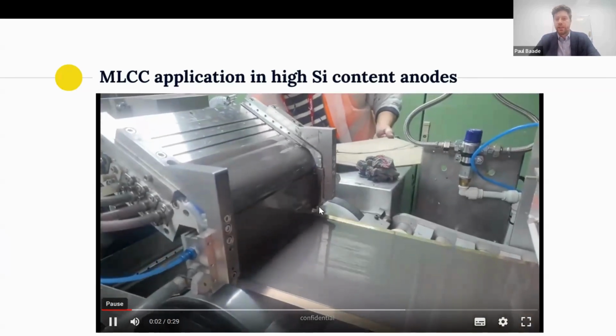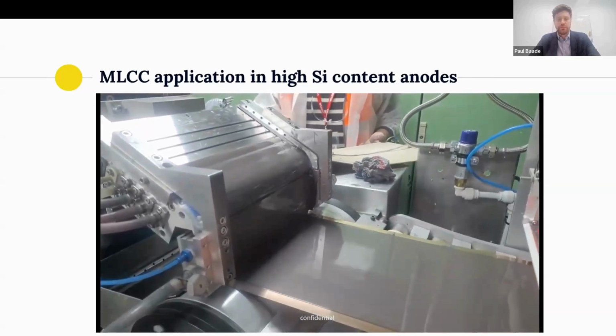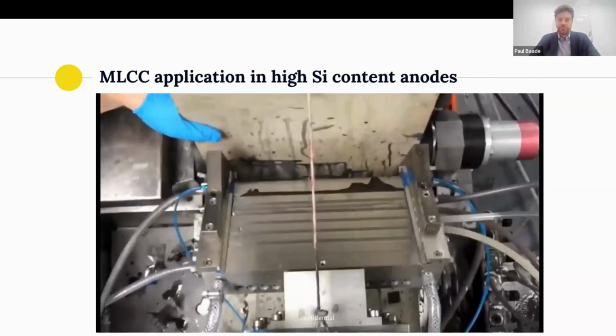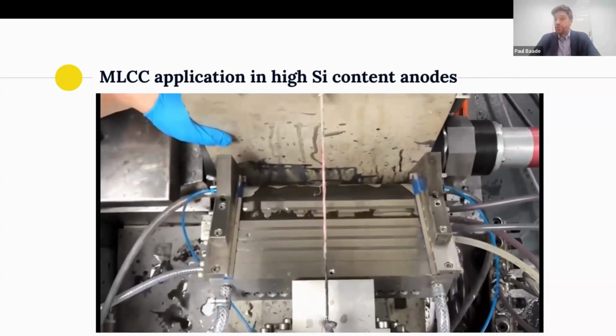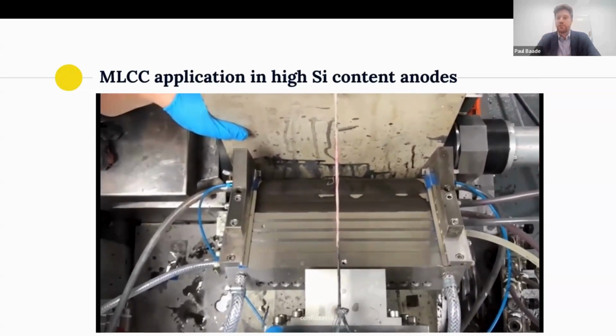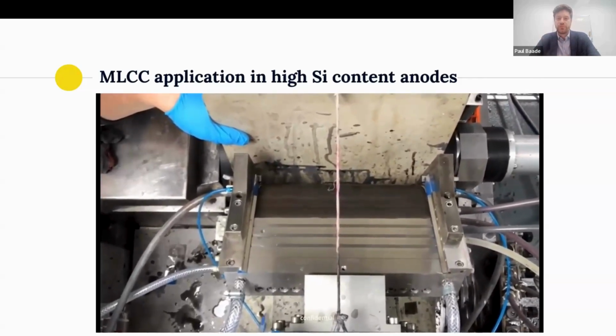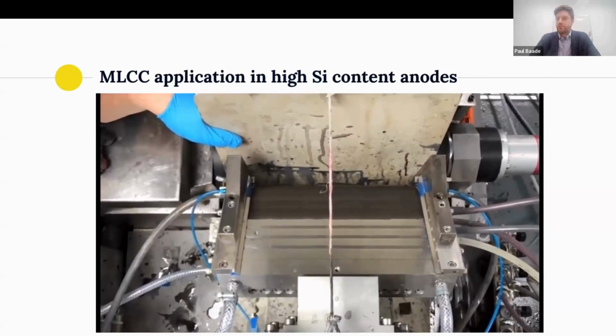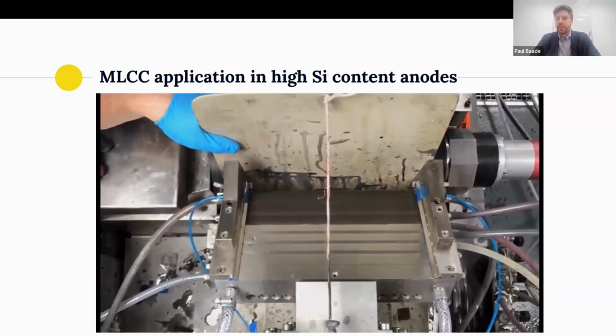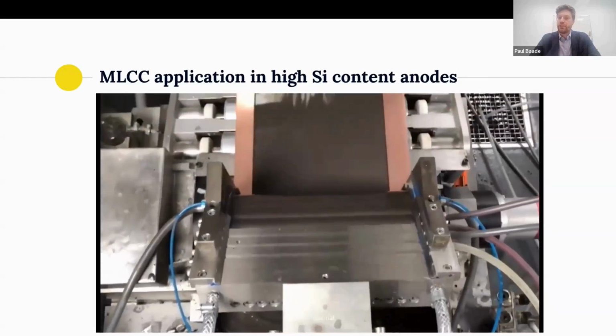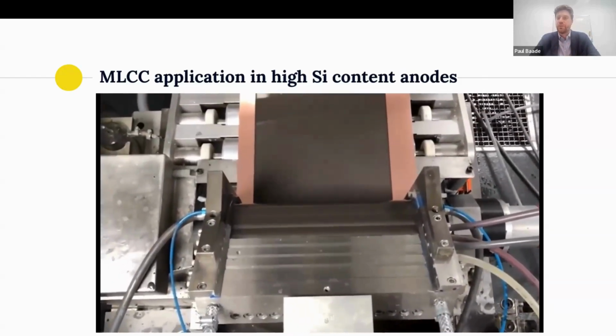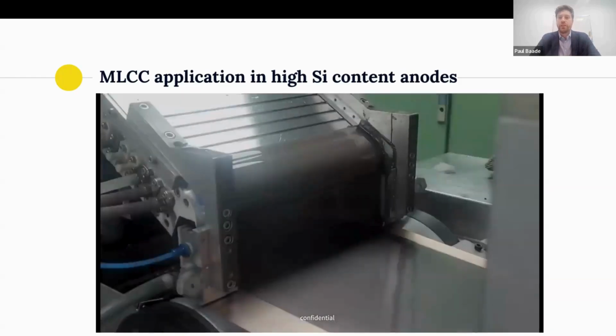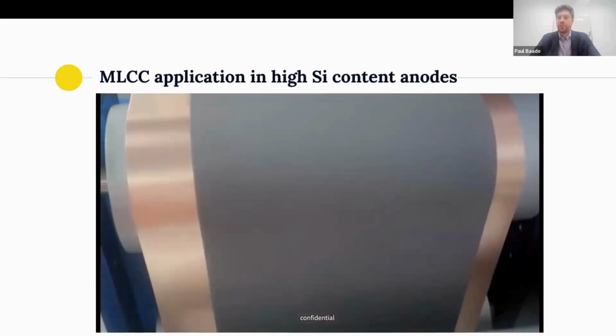And today, actually, I brought a video of our pilot trials here, where we deposited a silicon anode at 250 meters per minute coating speed. It was actually a triple layer fashion to work around production requirements. And you can see the process here live in action. You have the multi-layer curtain die, 3 layers of the same material being deposited, and I believe this video is actually at 250 meters per minute.